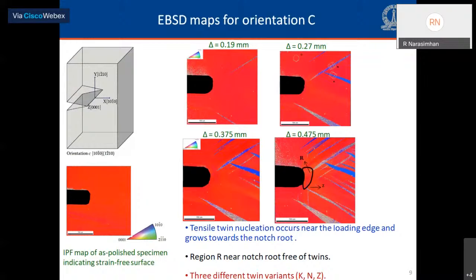Unlike in the case of orientation A and B, where the twinning started from the notch root and started emanating out from the notch root, here we see that it commences at the far edge of the specimen, where there is a compressive global bending stress field, which in this particular orientation is favorable for extension twinning. And that set of twins propagate towards the notch root, as you can see by following the sequence of images. And at very large load point displacement, however, there is a region identified as R in my bottom right side image, which is still free of twins. And we also see 3 twin variants in this case, as opposed to the other case where we saw 2 twin variants.